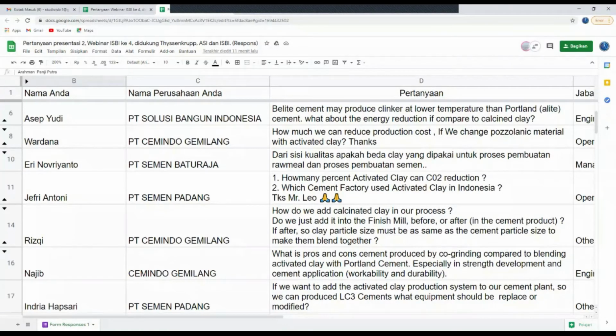So how do we add calcined clay in our process? Do we just add it into the finish mill, before or after? If after, the clay particle size must be the same as the cement particle size to make them blend together. Okay, so there are several options here. The first option would be to put it together with clinker in one mill, for example a ball mill, and grind it together, an intergrinding.